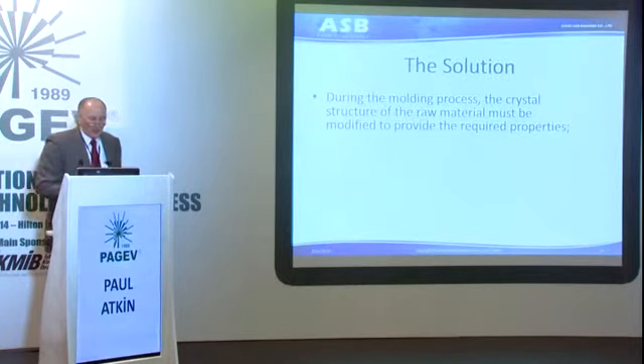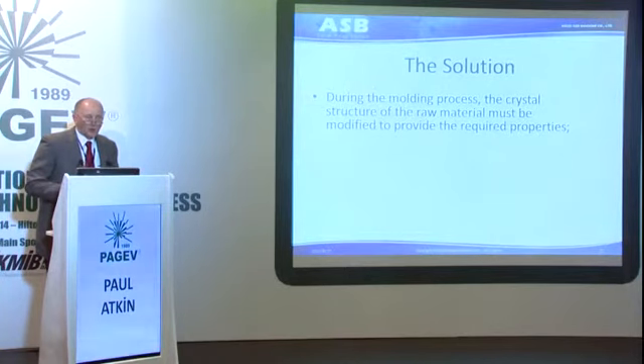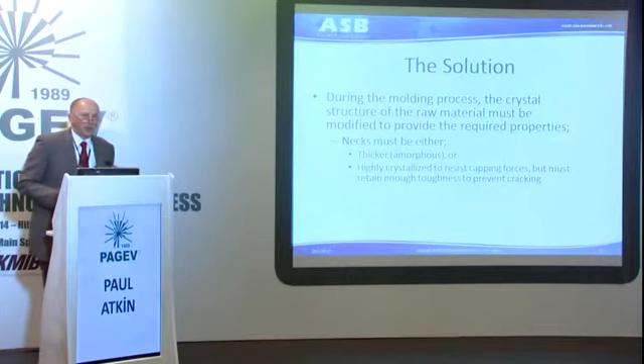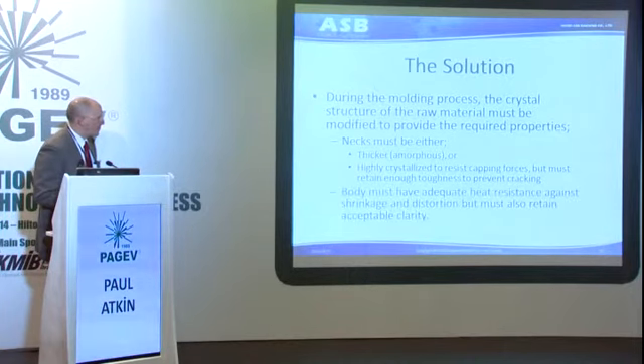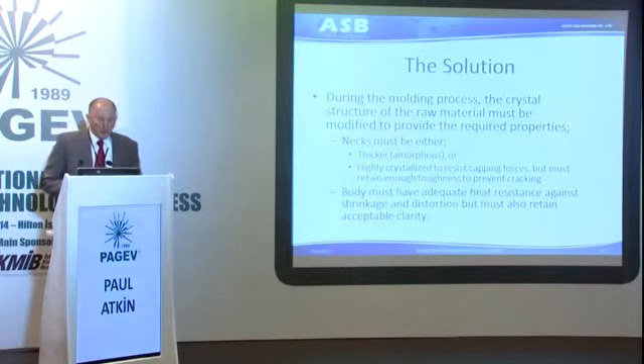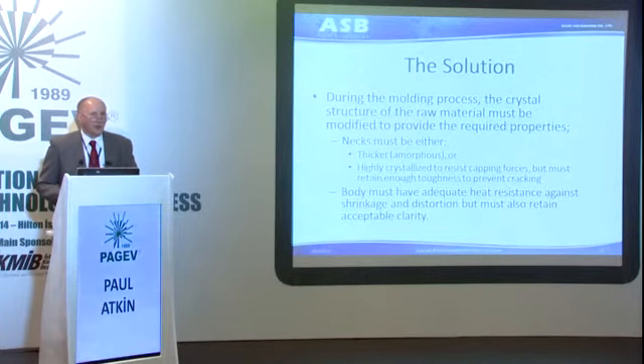So the solution. During the molding process, we have to modify the crystal structure of the PET. Now, in the neck, in some cases, you don't need to do anything with the neck. If it's a relatively low temperature fill, a plastic cap, a strong neck, you can sometimes just use a thicker neck and keep it amorphous. But generally, a crystallized neck, especially for the jars, will be absolutely necessary. In the body, well, we need to have good heat resistance, and that means creating crystals. But if we create too many crystals, we achieve a hazy appearance. It's not clear. So we still need to keep the clarity, but also get the heat resistance.